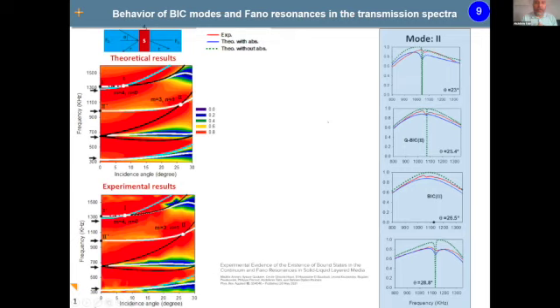And here we see the comparison between the theoretical result and the experimental result. On the left, the graph represents the transmission, with the different points coming from experiment and theory. We can identify by 1, 2, 3 the different positions of bound states, but what is interesting is the right curve. At an incidence of 23 degrees, the red and blue curves are theoretical and experimental. The green one is the theoretical without absorption.